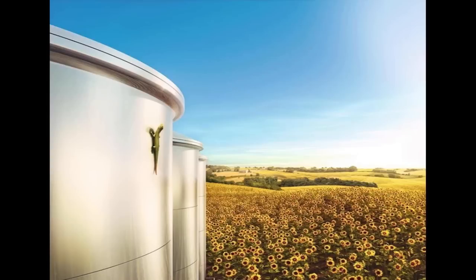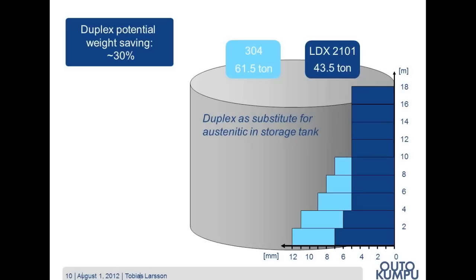Now we'll take a look at a theoretical example in the shape of a stainless steel storage tank. Here we have a storage tank that is 18 meters high and with a diameter of 18 meters as well. The light blue staples represents the wall thickness of the austenitic grade 304, and the dark blue staples represents the wall thickness of the duplex grade LDX2101. So in the austenitic case, starting from the bottom of the tank, you will have to use a thickness of 12 millimeters, going to 11 millimeters, 9 millimeters, 8 millimeters, 7, and then 5 millimeter in the upper part.